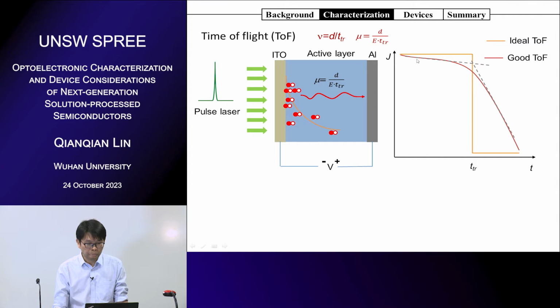You can get a kind of kink from here. So the kink is almost close to the ideal transient time, and you also have some deviation from the kink because the charge transport is very dispersive. First, we photo-generated the carriers. It follows the Beer-Lambert law. So some photons could be absorbed just in front of the material, very close to the electrodes. Or some photons can penetrate much deeper, and it follows the Beer-Lambert law, right? So some carriers can be generated much deeper inside the active layer. So if these electrons go to the counter electrode, they have a much shorter distance. That's why we get a dispersive transient curve.